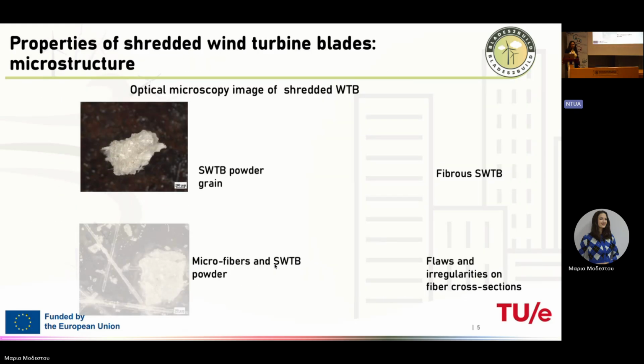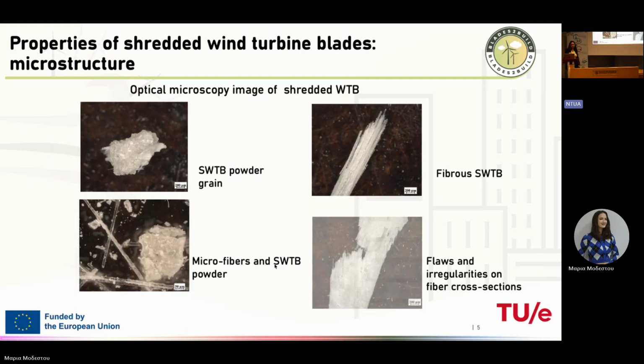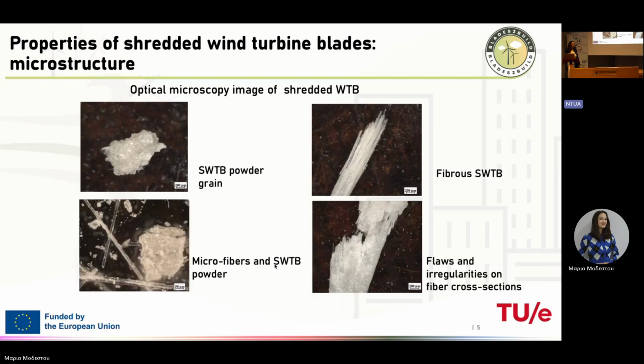So what we see in optical microscopy is this variety and these imperfect particles, with some powder grains which contain more polymer. We had a mix of microfibers and powder. We have fiber, basically glass fiber, which is glued together with polymer. We have flaws and irregularities on the fiber cross section, basically after shredding and damage.